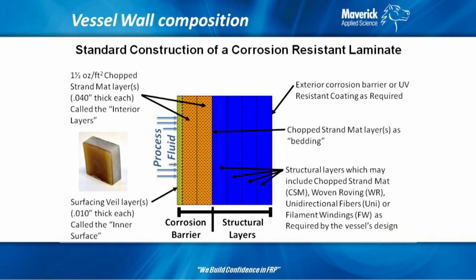One thing to keep in mind with this too is once you see corrosion has gone through your primary corrosion barrier and is into your structural laminate, because the percentage of resin is much lower in the structural laminates, it will typically accelerate the corrosion through the structural wall much faster than it went through the corrosion barrier. Because the corrosion barrier is built to stop corrosion. Structural wall is built to help hold the corrosion barrier together.